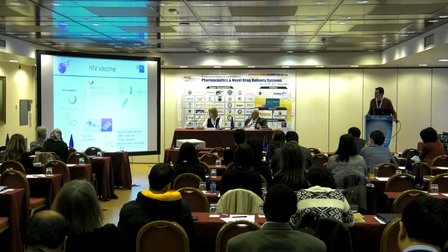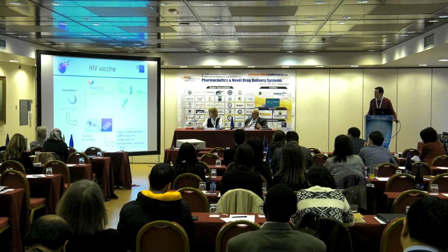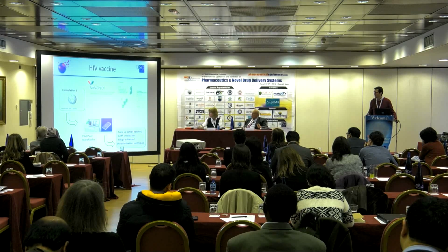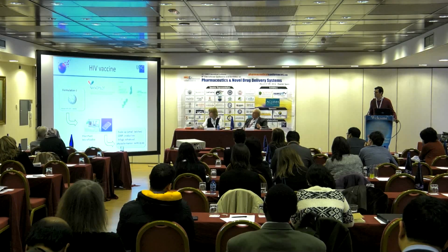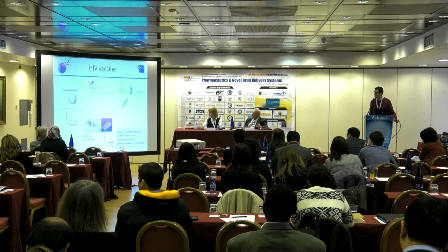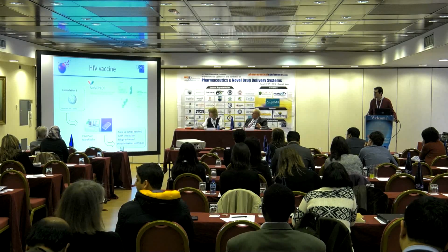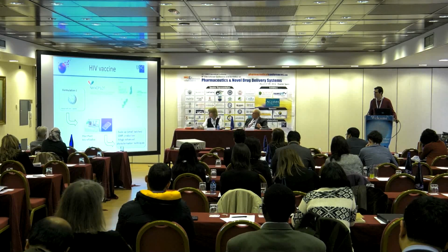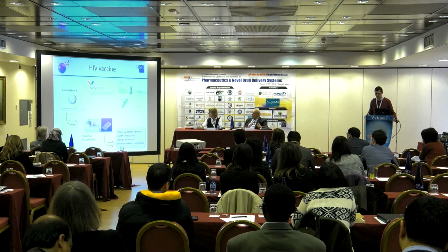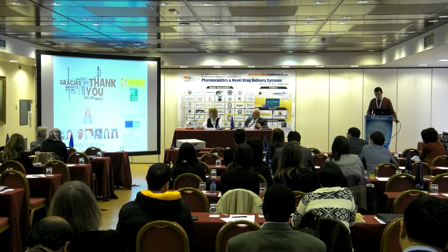This formulation is quite important, so we got involved in another European project, the NanoPilot. The main objective of this project is to scale up a formulation, in this case the chitosan nanoparticles with 1 peptide, using microfluidics to have a continuous way of preparing the nanoparticles, using GMP materials and production with highly advanced characterization techniques. And this is all.